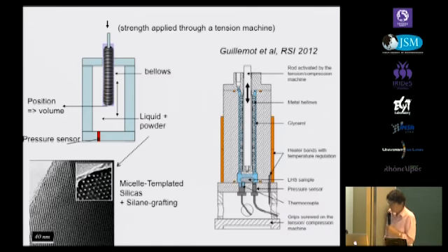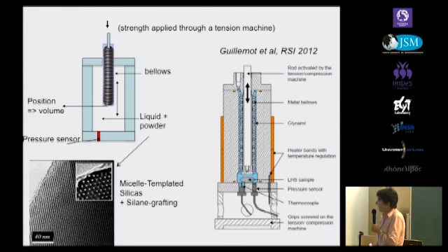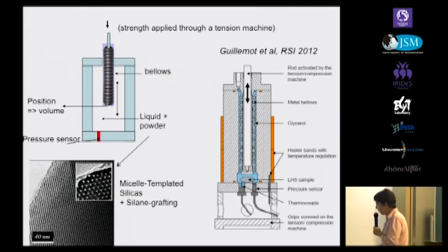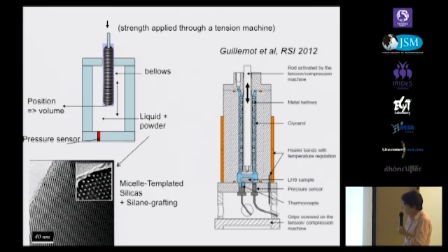We have studied the behavior of lyophobic heterogeneous systems using a specifically designed high-pressure cell and a traction-compression machine. We have studied model porous media, which are micelle-templated silicas made hydrophobic by silane grafting.